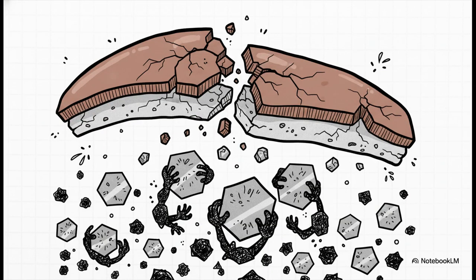To put this into perspective with some actual numbers, high-quality stainless steel relies on having about 18% free chromium perfectly distributed throughout the metal to create its protective layer. But during sensitization, because the carbon acts like a thief and steals that chromium, the free chromium levels in those local areas plummet from 18% all the way down to just 6%. The stainless steel is completely starved of its armor, leaving it totally defenseless.